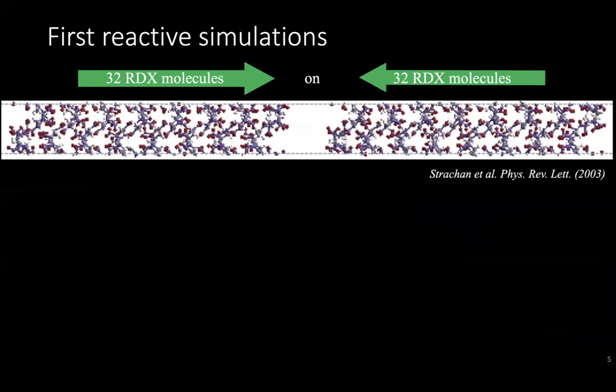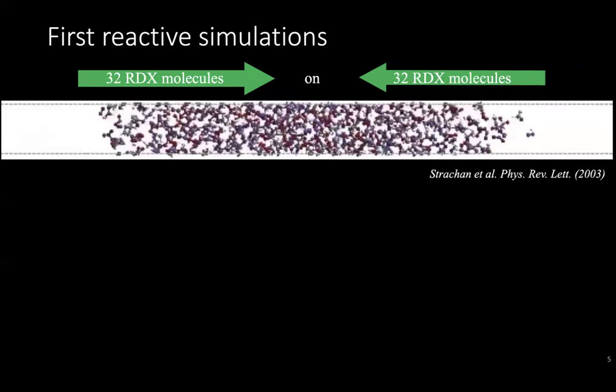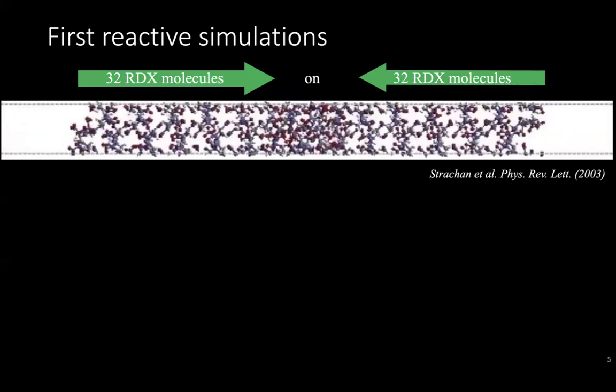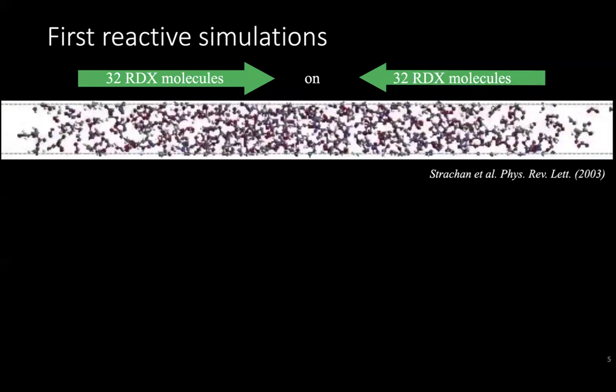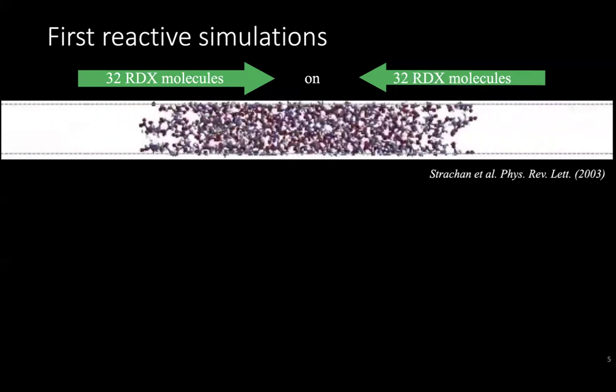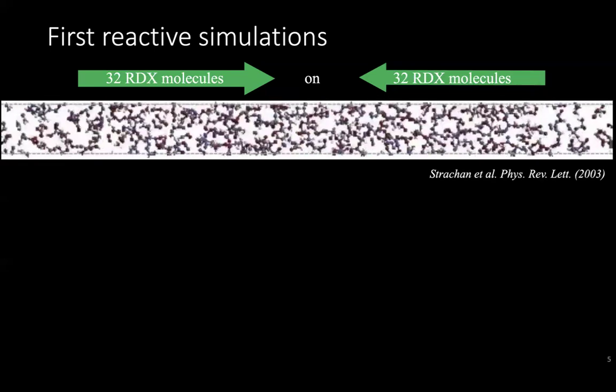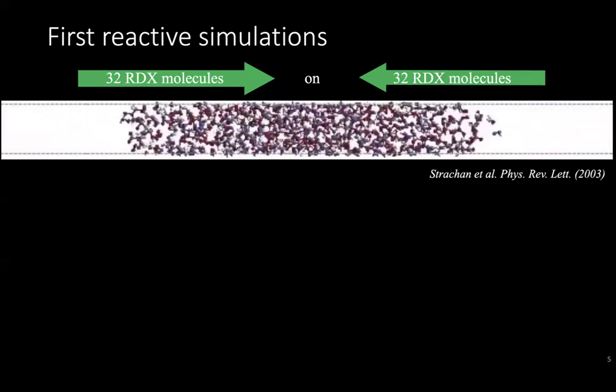So I joined the field in the early 2000s. And in those days, for the first time, we had the ability to do molecular dynamics with reactive force fields that could break bonds and form bonds. And so we decided to look at mechanochemistry. So we decided to take this molecular crystal called RDX, an energetic material, and smash it into itself and create a shock. So we would put mechanical energy into the system. That shock heats up the system and compresses the system, and eventually it leads to chemical reactions. What we saw out of this first ever dynamical simulation of mechanochemistry at extreme conditions is that bonds were breaking super fast, right at the shock front.